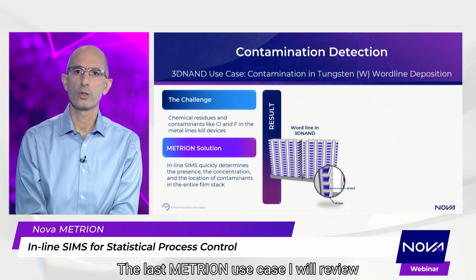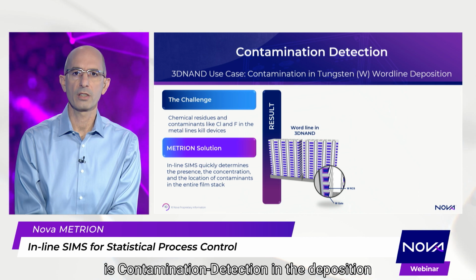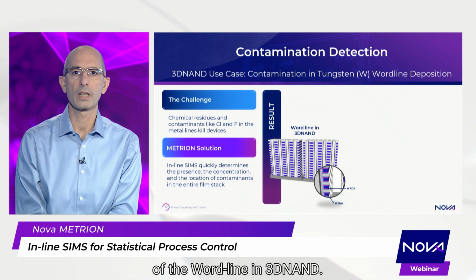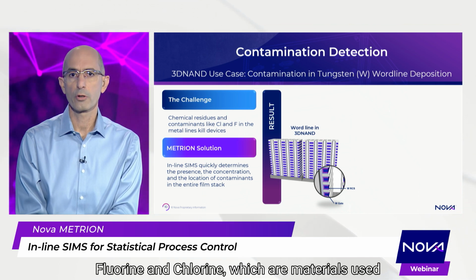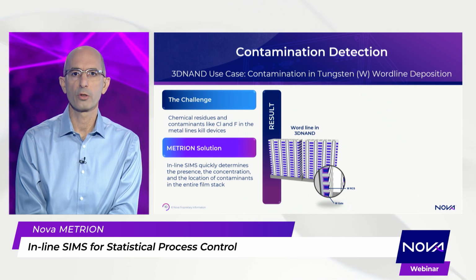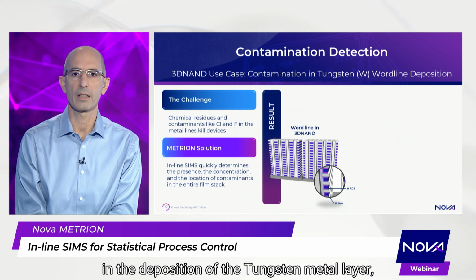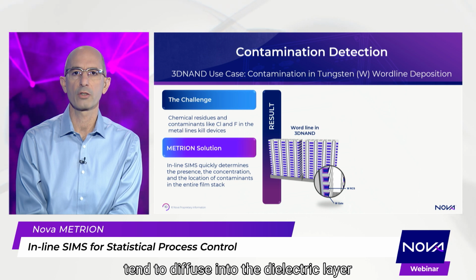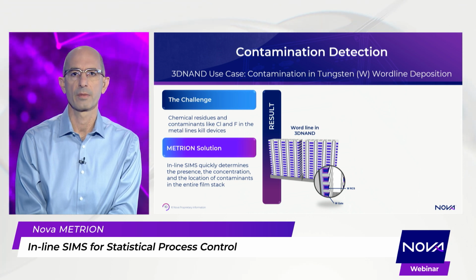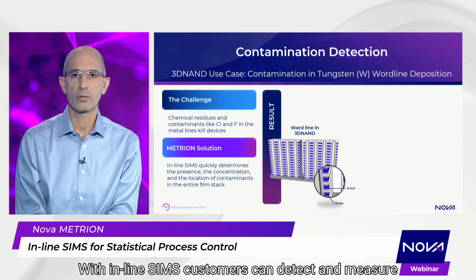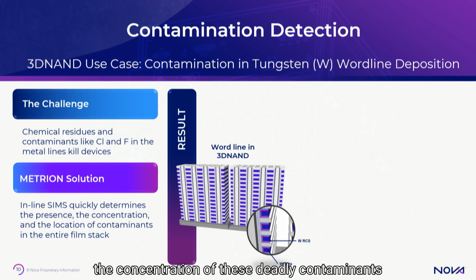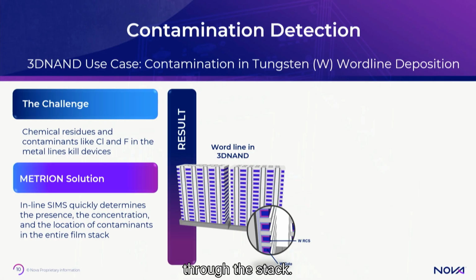The last METRION use case I will review is contamination detection in the deposition of the word line in 3D NAND. Fluorine and chlorine, which are materials used in the deposition of the tungsten metal layer, tend to diffuse into the dielectric layer and can kill the device. With inline SIMS, customers can detect and measure the concentration of these deadly contaminants through the stack.